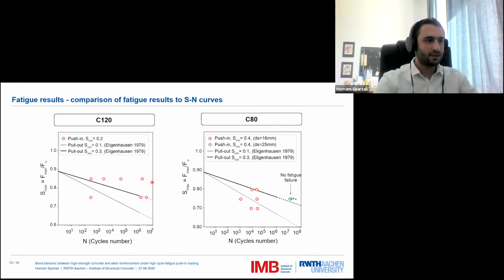Actually, this is just scatter that is somehow usual in fatigue experiments for bond, because in concrete already, if you test pure concrete specimens, you will also see large scatter. But in bond that is 2.5 diameters, that means about 4 centimeters for the case of steel of 16 millimeters, it's a really short bond, and yeah, it's normal. For example, in the results of Eligehausen, if you look at his paper, you will also sometimes see a really large scatter.